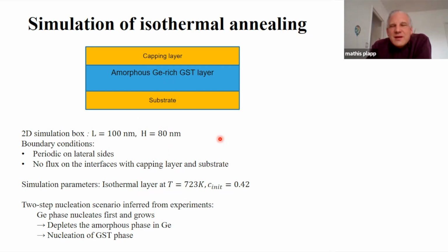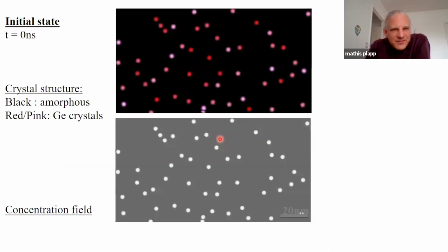And then when the germanium grains grow, the matrix gets more and more depleted in germanium until at some point the GST phase can nucleate. And this we handle by using classical nucleation theory. And when the probability of nucleating a GST is high enough, we put nuclei of the GST.